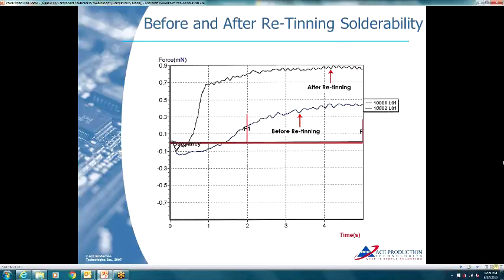Here's an example of using a wetting balance test to measure the difference before and after retinning. In other words, why do you need to tin parts? Parts are retinned for a variety of reasons: to remove oxides, to remove contaminants, to remove the gold. This was an actual case where it was a specialized component and the client could not solder it to the circuit board. I don't know if it was hand soldered or machine soldered, they just couldn't get it to solder.